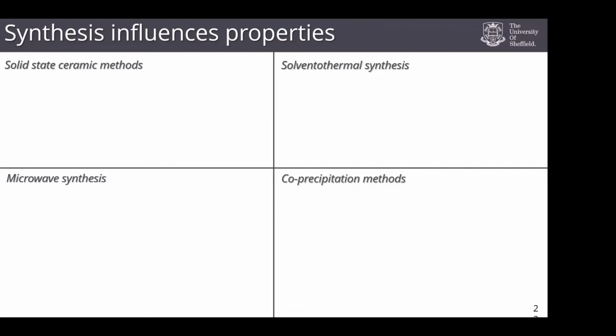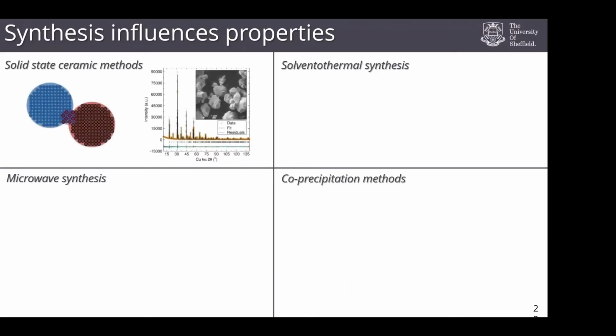So sometimes we use traditional methods like solid state ceramic methods. And that's where we take solid materials, and we mix them together intimately. So really grind them together so that they're touching and they're really well mixed. And we use elevated temperatures to essentially get these two solids to meet, mix, marry, and form whatever compound we want at that interface. So it requires a lot of heat, a lot of time, it's very energy intensive, but you get beautiful big particles. And this is showing you an X-ray diffraction pattern of what particles like this look like, really beautiful sharp peaks that tell us these are really crystalline.